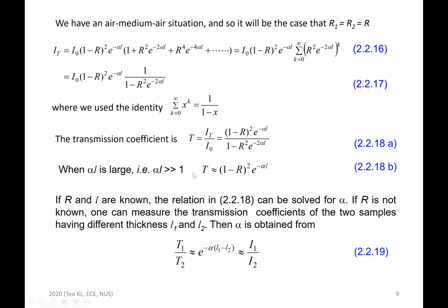If you know the reflection coefficient of a particular medium or semiconductor, and you know the thickness of the sample, then using either this equation or this equation, you can solve for the absorption coefficient.